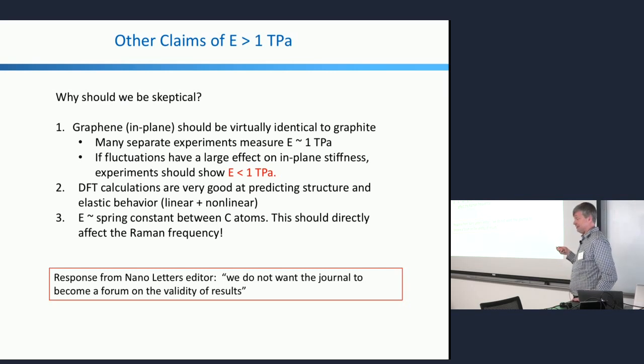The other thing is that Young's modulus is basically a spring constant, right? And if you have a spring constant and a mass, you have something called a frequency, right? And we measure those frequencies with Raman spectroscopy. If you had these variations in Young's modulus by factors of 2 or more, you'd expect to see Raman frequencies going all over the place. And they don't. They stay in the same place for monolayers and multilayers. So the whole thing makes me very skeptical.